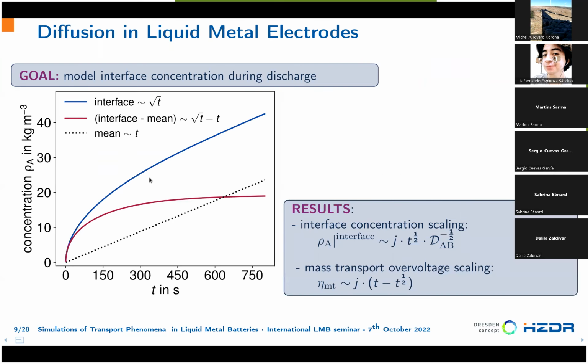We are really interested in the evolution in time of the difference of concentration between the interface and the mean, because this is a measure of the mass transport overvoltage. And with the simple model, we can see that this scales as a square root of time. It's also important to see that the interface concentration scales as the first power of the current density, and therefore the mass transport overvoltage will follow this scaling.